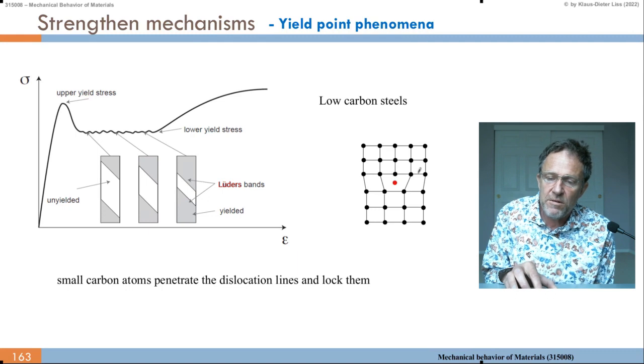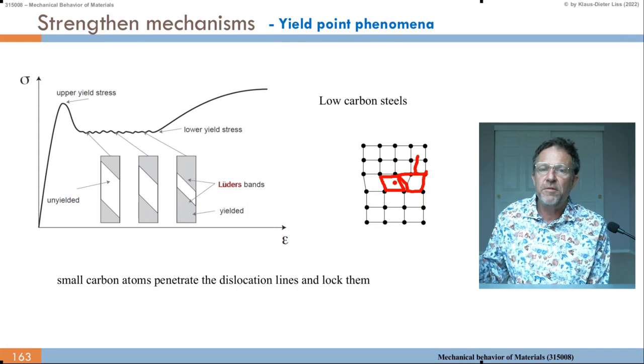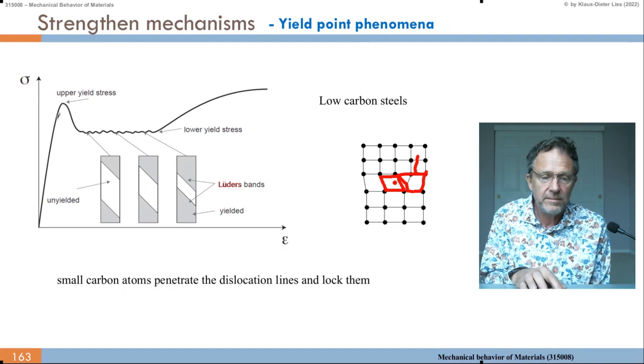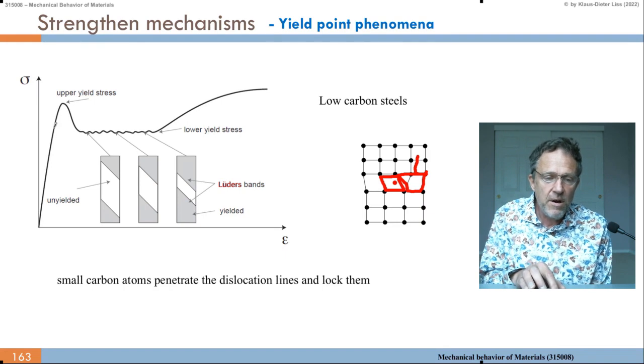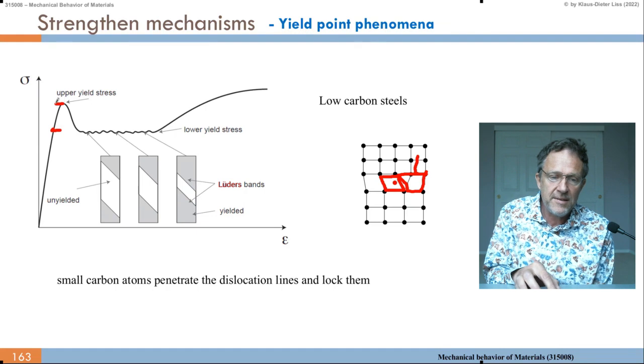Now if I want to move the dislocation from here to there, then I need to compress this cell with the carbon inside and get the larger cell there. And that costs energy because I need to compress the carbon. So I need to overcome this energy to compress the carbon. And then the dislocation can move freely, and the carbon we leave behind. So that's what's happening here. I need to overcome this extra stress to compress the carbon, this stress amplitude. And then once the dislocation is moving, then it becomes easier again, because I don't meet carbon atoms.